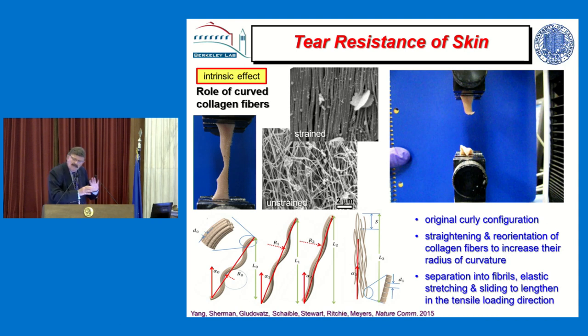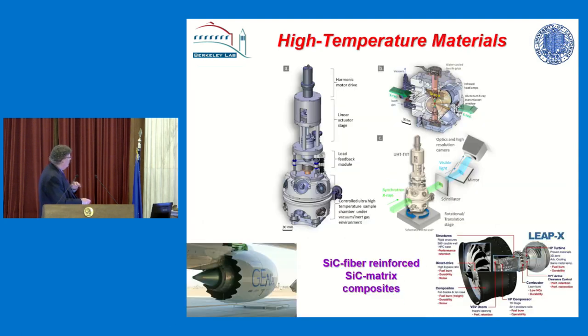Of course, there are certain directions in skin which are more resistant, and that's used in surgery, but I won't talk about that now. Now, to change the subject, what about engineering materials? What's happening there? Well, I think the two biggest things that have happened in recent times in terms of the damage tolerance of materials has been the adoption of ceramics in gas turbine engines. We've always wanted to have ceramics. They're much lighter. They have a much higher temperature range than metallic alloys like nickel-based superalloys, but they're brittle.